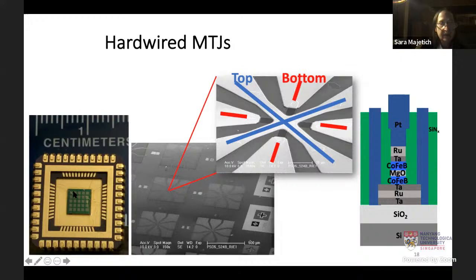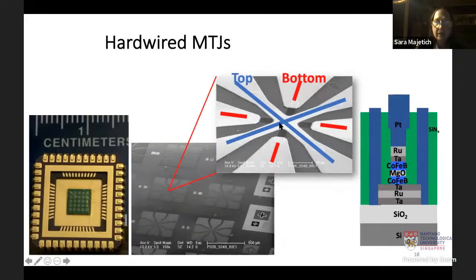If you look at the individual devices in SEM, there are these flower patterns, and in the flower pattern, the little X's on one level are the top connections. So we have 4 places we could wire bond, and the other red connections are the bottom electrode connectors. So if we look at a side view of our MTJ, we still have the MTJ on the inside, but now instead of being a bare pillar, we have it surrounded by silicon nitride. So that prevents edge oxidation.